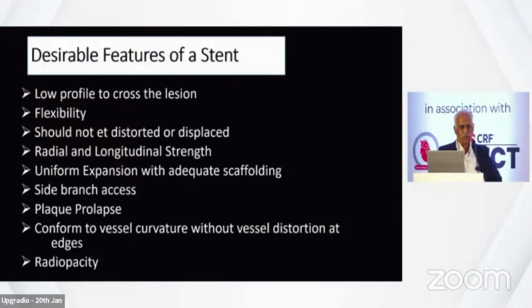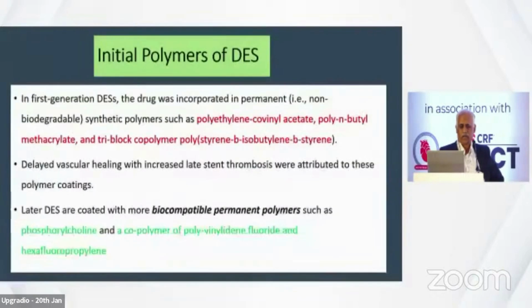It should be flexible to go through tortuous vessels. Should not get distorted or displaced. Enough longitudinal strength should be there. Radial strength should be there, especially if you're using it for ostial or calcific lesions. You should have uniform expansion. Side branch access should be there. Plaque prolapse should not be there. And it should conform to the vessel curvature without vessel distortion at the edges. Otherwise, you may have vessel dissections or late stent fractures. And it should be radiopaque enough.